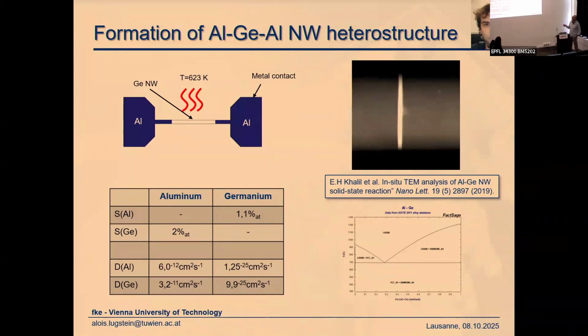As soon as you have 1% of germanium dissolved in the aluminum, this process stops. Then you can heat it up for hours, and the interface will remain at the same position. So you have to guarantee a huge reservoir where you can dissolve the germanium. Germanium penetrates into aluminum? Yeah.